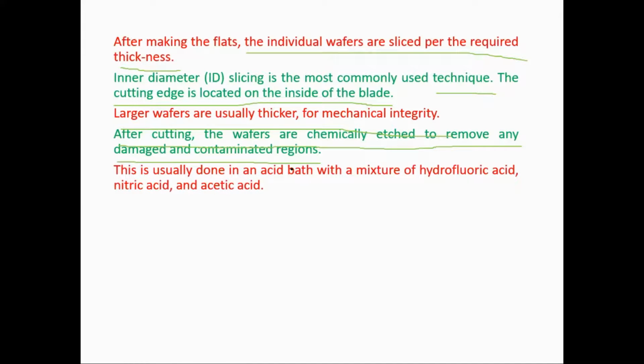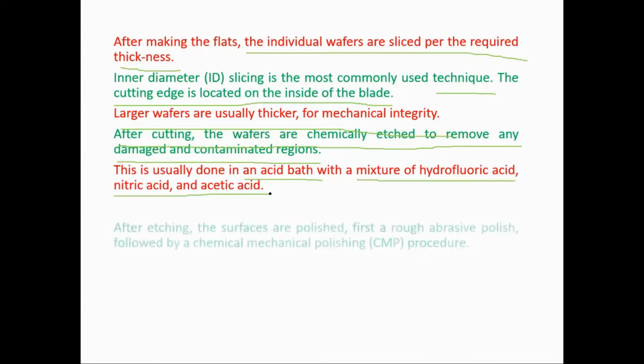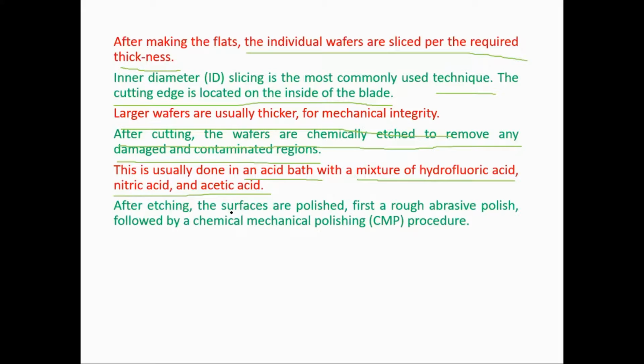This is not done with a normal chemical. It is done with an acid bath, and a mixture of hydrofluoric acid, nitric acid and acetic acid is used to get this chemical cleaning done. After the etching, the surfaces are polished because the surface is rough. A rough abrasive polish followed by chemical mechanical polishing is done. This is quite similar to how marble is ground in your homes and after that polishing is done. But that is for marble.